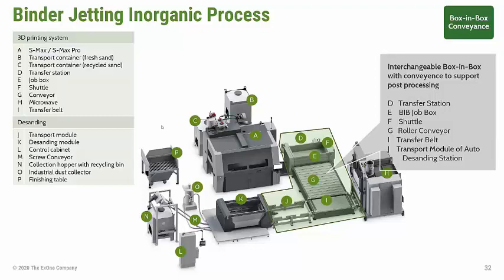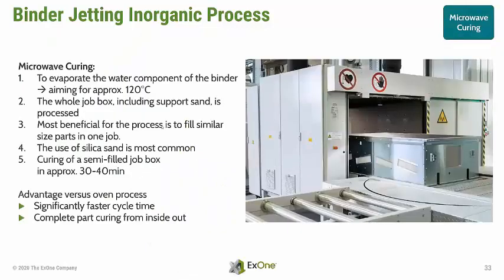After microwave curing, the job box will transfer over to the auto-descending station. Before we talk about this station, I would like to spend a moment on the microwave process step. The microwave, developed by ExOne, has just one duty. It helps to evaporate the water component of the binder and therefore aims to get to an operation temperature of about 120 degrees Celsius. We're heating the whole job box at a time, including the support sand, in a time of only about 30 to 40 minutes.